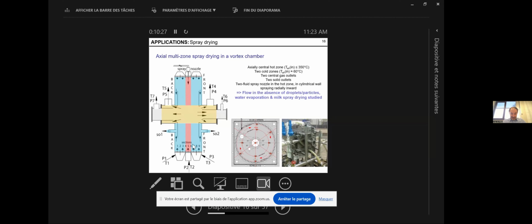And the reason for that is that the high centrifugal force that you have here is like a wall for the gas coming in. And the centrifugal force is a little bit lower near the end plates of the chamber, here, near the end plates. Yeah? And because the centrifugal force is lower here, the centrifugal pressure is less, and the gas, the air, immediately seeks the easiest way out, and that is near those end walls. And so you get that kind of motion. Yeah, you get a secondary motion, which implies recirculations here in this chamber, and actually outward motion in the center. Not inward, but outward motion in the center. And so you have very strong axial mixing.